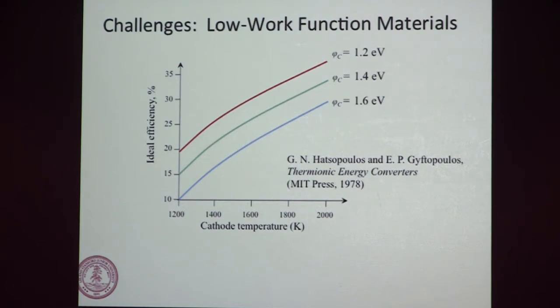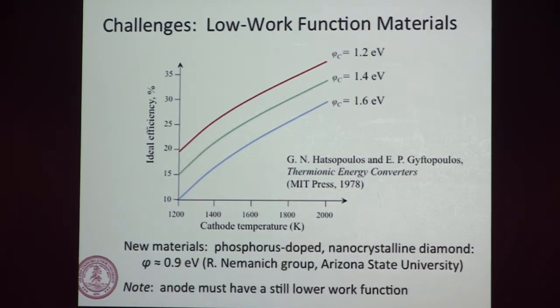So back in this early era, if you look at the efficiency as a function of various work functions and the cathode temperature, there's a huge incentive. Remember, we were at 3 point something eV, way out of what would be reasonable. But if you get down into these lower work functions for the cathode, and of course the anode has to be even lower, you can get very impressive efficiencies that would become quite interesting. Nemanich's group at Arizona State has published papers with nanocrystalline diamond where they have work functions of 0.9 eV. And that would be a new material.